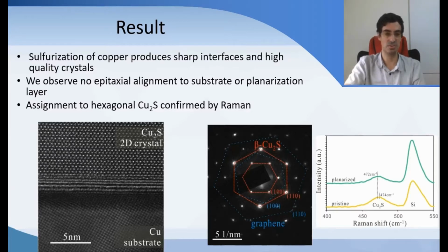In our case, we're using sulfur and copper, and we see that a planar 2D crystal of copper sulfide is formed, whereas the copper substrate has a very sharp interface with that crystal. The graphene in this case is not visible in the cross-sectional TEM image, but we can see the presence of graphene from a diffraction image of the basal plane.